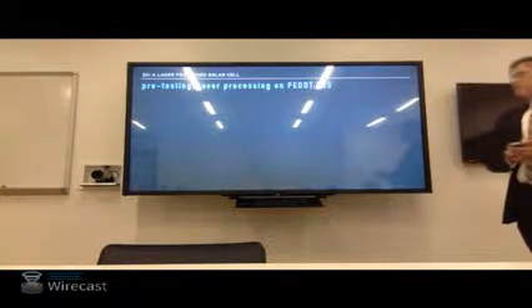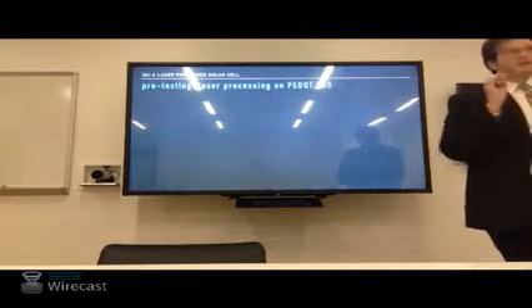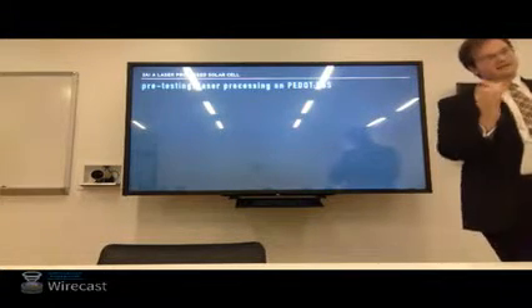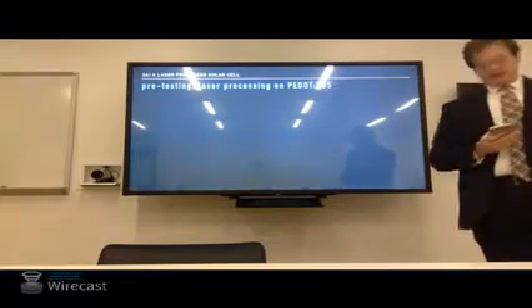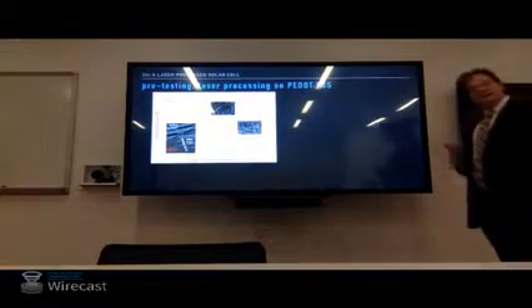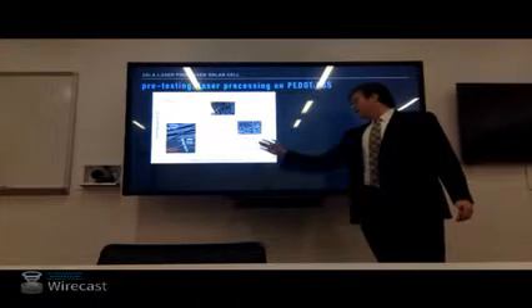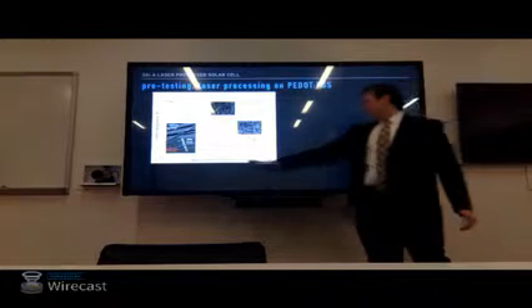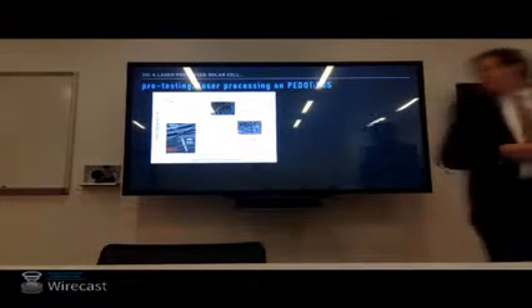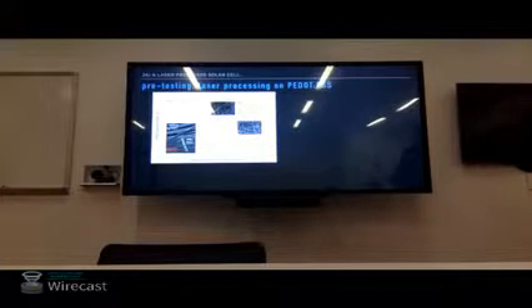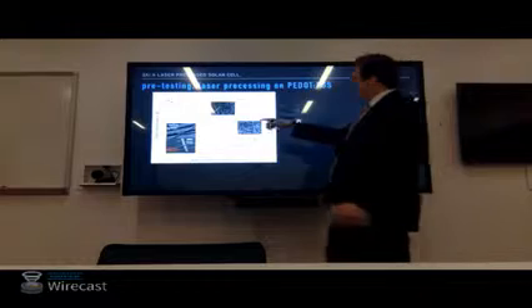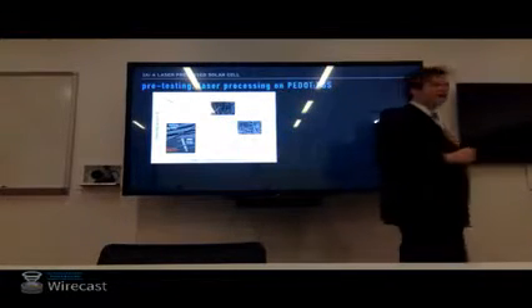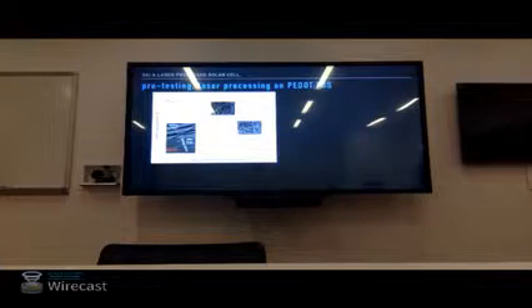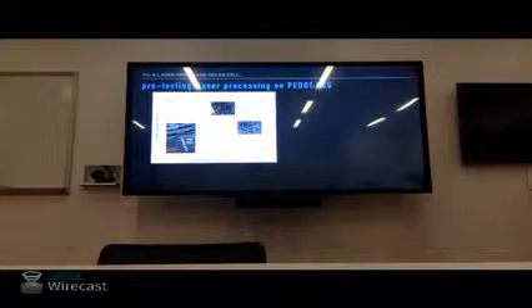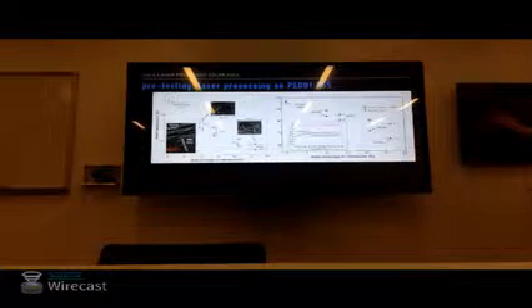Before we make devices, there's some salient pre-testing that needs to be done. The laser processing I discussed just a moment ago deals with nanowires on glass. Now we have nanowires on PEDOT:PSS, a slightly different system. So again, we can make a variety of nanowire networks. Here, as a function of area coverage of nanowires, we track the sheet resistance before and after the laser process. Important also to note on this plot, we have a point at 0% area coverage. That's only PEDOT:PSS. This is to verify that the laser process isn't doing anything to the sheet resistance of our sensitive organic semiconductor.